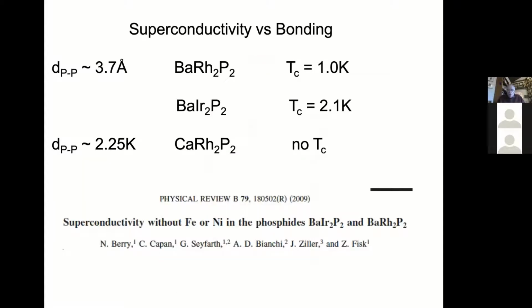So some experiments that were done on these rather low TC materials show that for these phosphides, in the long lengths, you have superconductivity showing up. And for the short lengths, you don't get TC, at least not down to 0.4 Kelvin. And so my thinking about this is that when you have the bonding, you've satisfied some tension, if you want to call it that, in the material. The bonding takes away that tension that's existing here when you don't get the pnictide bonding between these layers.